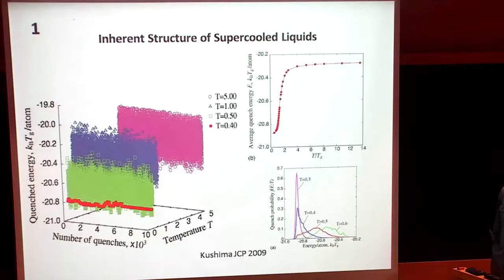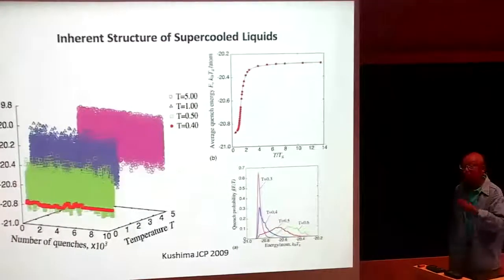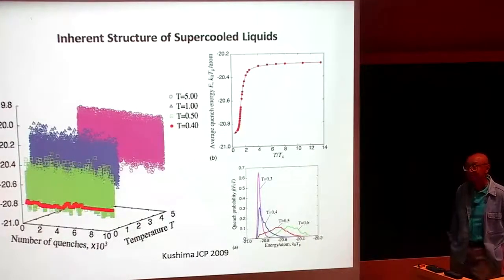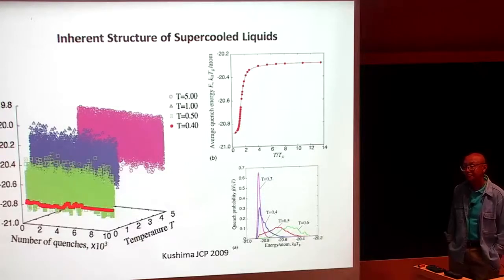Could I make a quick comment on this? It's related to earlier questions about the quench rate effect. Experimentally, if you look at how viscosity is measured, basically you cool the liquid down to a certain temperature. In glass, it's the same thing. You basically warm it up to a different, higher temperature. You make sure you have sufficient time for the system to equilibrate, so that it doesn't change. In that sense, the quench rate is not really in play. Otherwise, you would have history dependence in your viscosity.